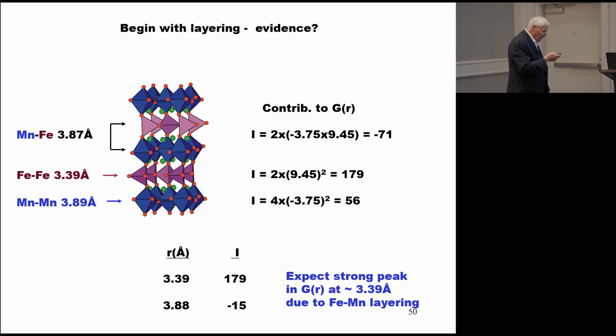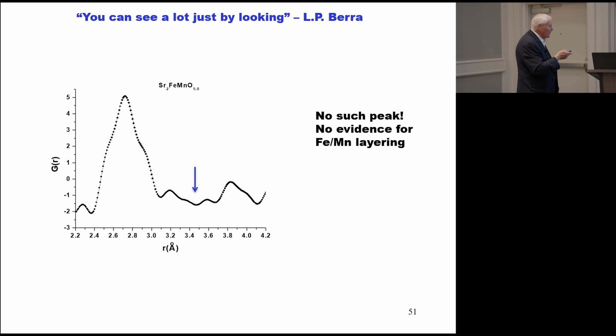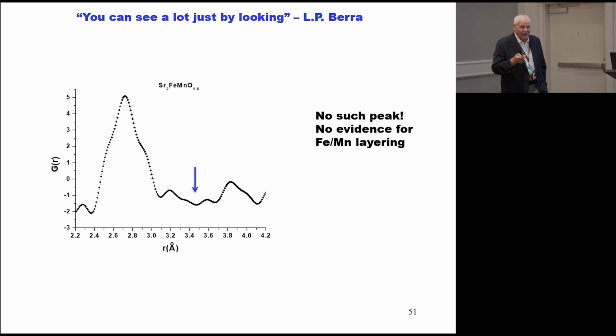I won't go into a lot of detail on this slide, but you can work out where you should see peaks in the G of R just by looking, not by doing anything fancy, just by looking at the damn thing. And so the end result of this analysis is that in the G of R itself, you should see a strong peak at about 3.4 angstroms and practically nothing at 3.89. Okay, what do we actually see? I'd like to paraphrase one of the 20th century's more interesting thinkers, Lawrence P. Berra.